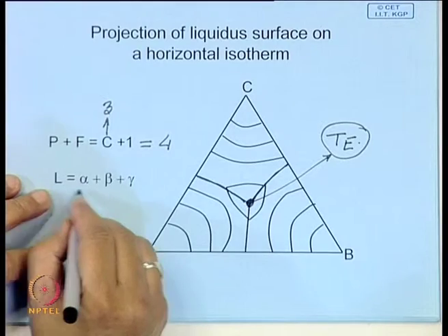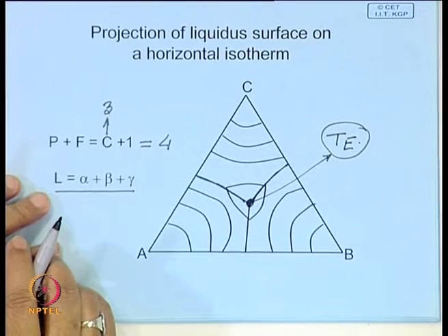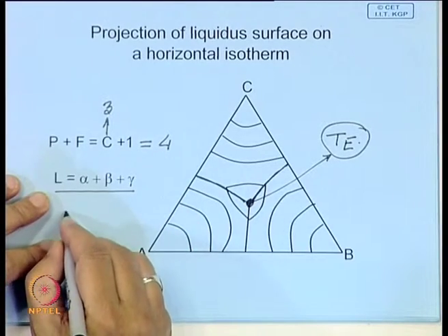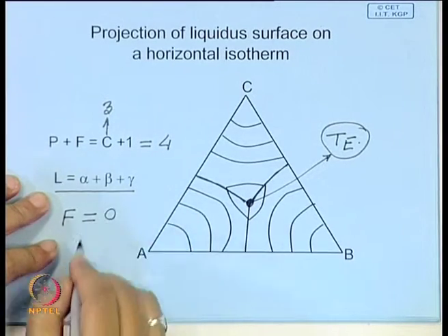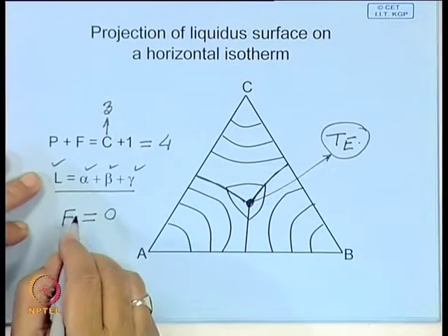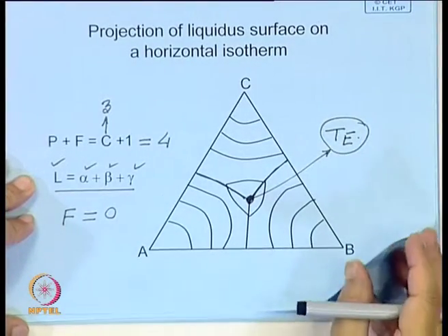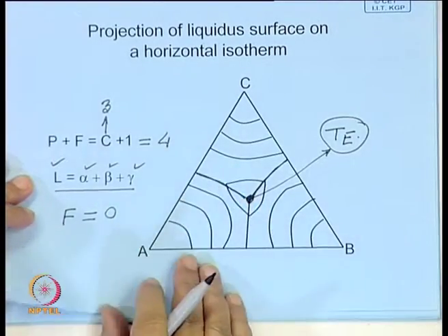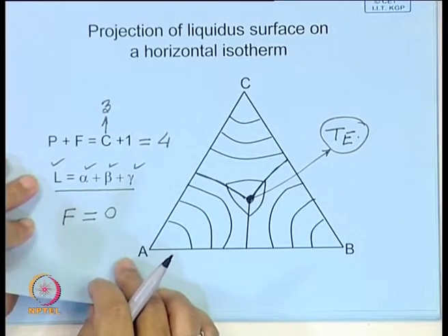When this eutectic reaction takes place, 4 phases are coexisting, so the degree of freedom becomes 0. That means the composition of the liquid and each of the solid phases will be fixed. Later on we will solve a simple problem to show how to find that eutectic temperature, assuming the liquid solution to be ideal and assuming there is no solubility in the solid state.